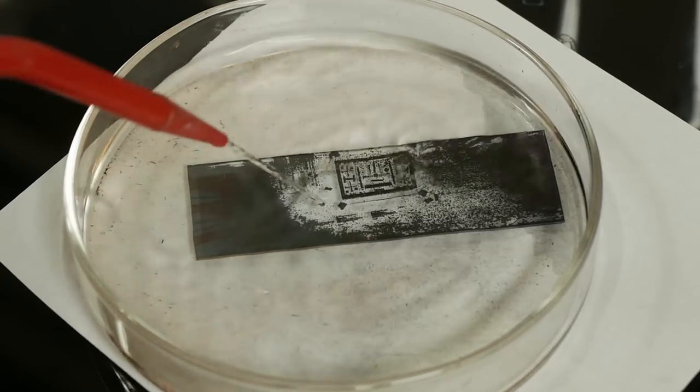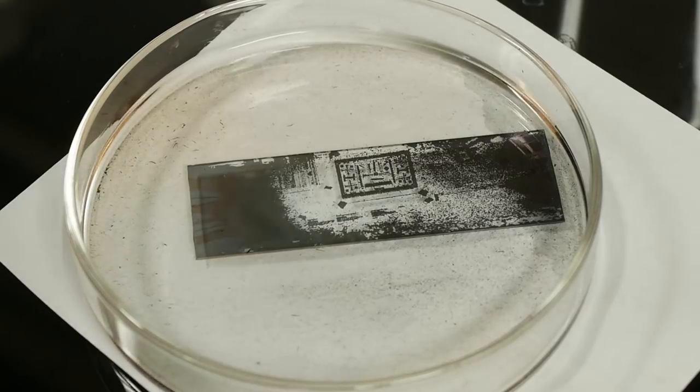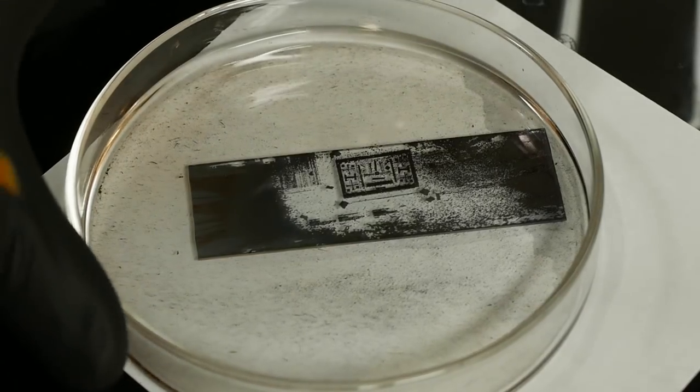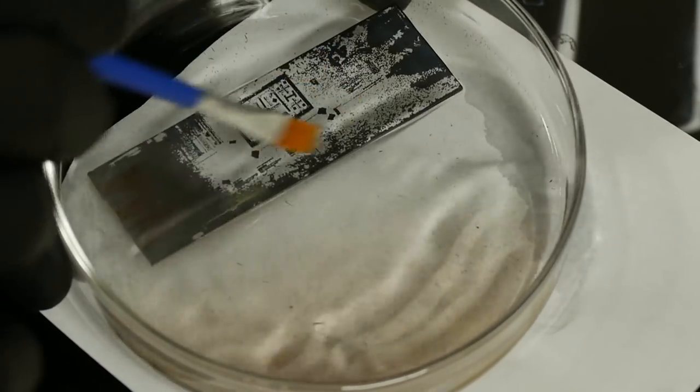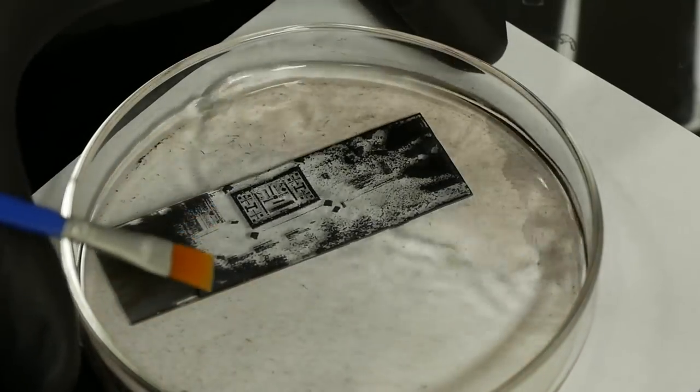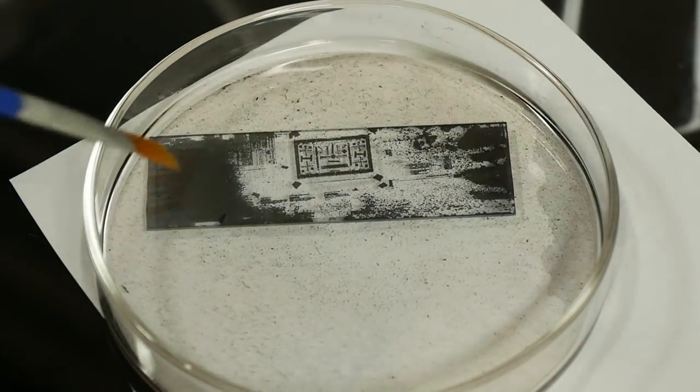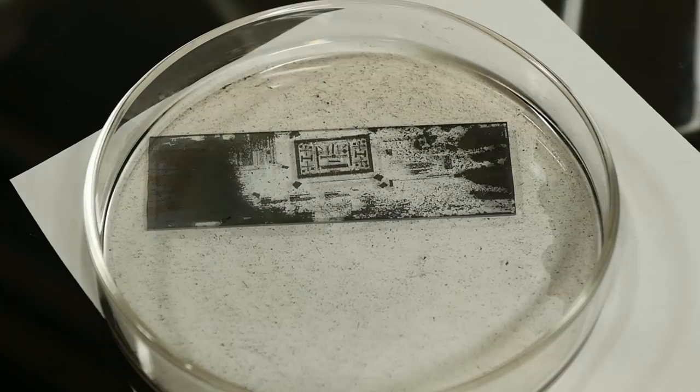And as I give it a little bit of very light brushing, it'll get through the rest of it. And the trick is that the titanium sticks so well to the glass. It's actually used as an adhesion layer. We're not really in any danger of brushing the titanium off.